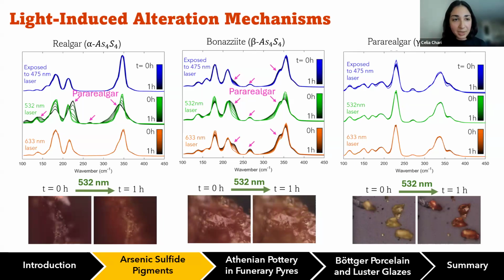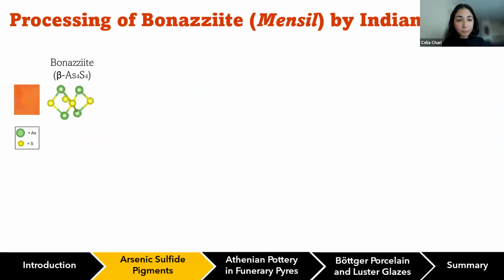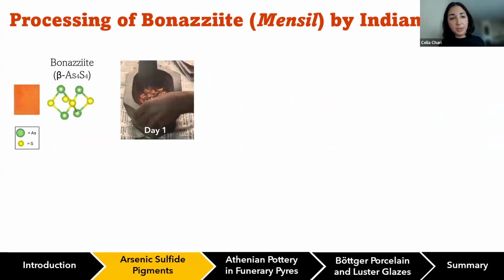So how does this relate back to the artists that we were working with? Knowing that bonazziite is so sensitive to light, much more than even realgar is, I asked the artist that I was working with whether he noticed any differences when he worked with bonazziite. If initially working with it and applying that onto paintings, he observed over time that it turned more yellow, or if he didn't notice that at all. And I was surprised to learn from him that he had not noticed the pigment turning more yellow.